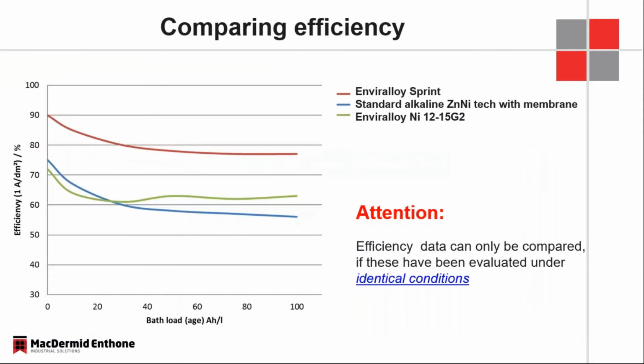So talking about numbers and efficiency, you can see that over time, standard alkaline technology will be reduced over a bath aging of approximately 100 amp hours per liter. The improved 12-15G2 is similar, although a little bit better, because it doesn't break down as much of the organic components. The Sprint process does have a reduction in efficiency, but we're starting out at a higher level of efficiency. And when it does reduce, it levels off at a higher level of efficiency. So the benefits between 60% and 80 to 90% are significant. Again, these comparisons are made against each other and are being operated under identical conditions.